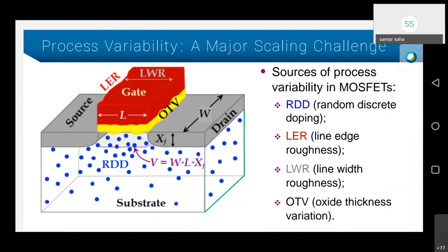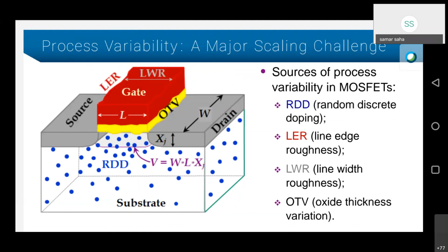On these 3D plots, all these blue dots are basically dopant atoms. That could be coming from source drain as well as channel, because we can calculate how many dopant atoms we have if we take about a 20 nanometer device, and then calculate from the volume and the junction depth. You can see that for about 20 nanometer devices, the number of dopants, or impurities, could be less than 50. So those are basically discrete, and they can go anywhere, instead of continuous, as we are used to knowing that the doping profile is continuous. But here, because of this low number, it is discrete.